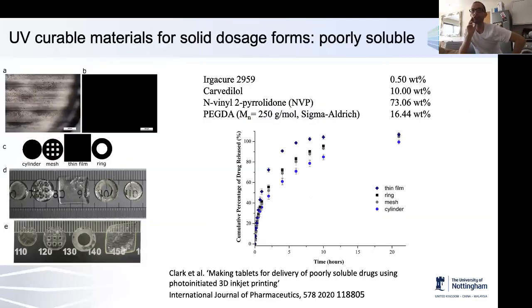Just to go back again to the formulation I talked about before for poorly soluble drugs, and you may have noticed when I put that slide up, they had different shapes. So there again, we were exploring the way in which shape could affect the release profile. And so we get different release profiles for different shapes, as you'd expect. But one of the things that we wanted to note, and was interesting here, is that previously a lot of the research in the literature has shown that you get very predictable release from different geometries, principally because it can be aligned to the surface to volume area and the diffusion path length.